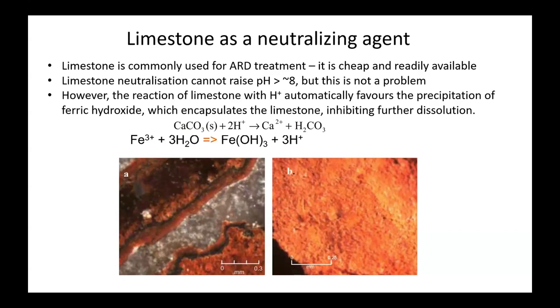So limestone is a good neutralizing agent. It's cheap. It occurs almost everywhere, not quite. It can't raise the pH to greater than 8. 8.2 is the pH of seawater, and that's the maximum that you can get using limestone in an acid rock drainage situation as well, but 8's plenty. The big problem with limestone is as it neutralizes the acid drainage, it causes ferric hydroxide to precipitate, and that precipitate coats the limestone gravel or the limestone grains, and then after a while it makes them inactive. They can't dissolve anything more.